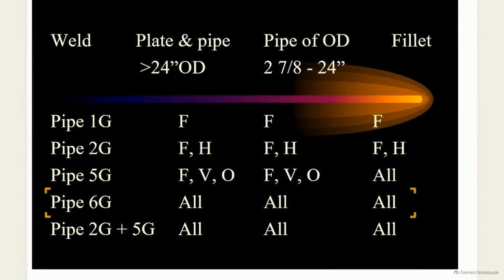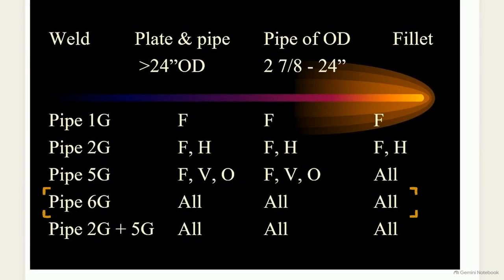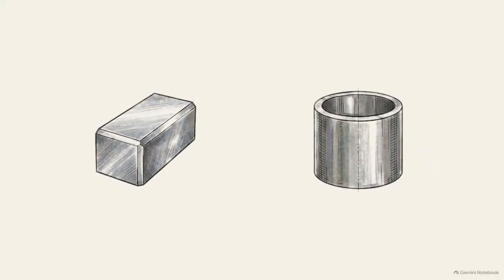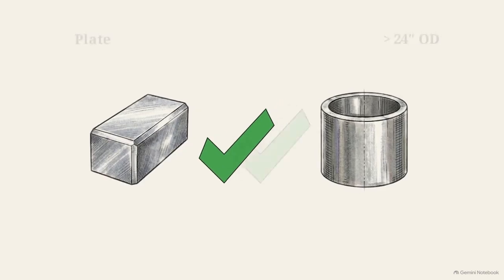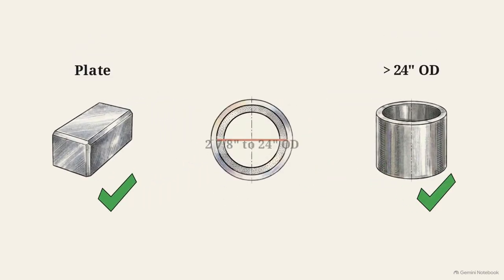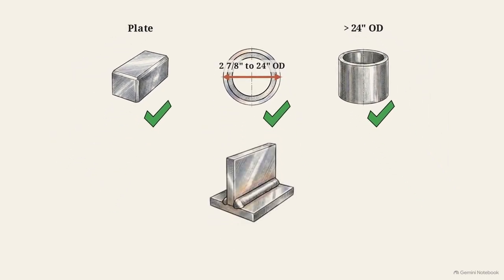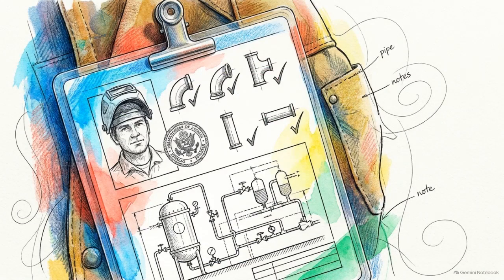We'll look at the fourth row labeled Pipe 6G. Note the designations in the subsequent columns. Successful completion of this test qualifies the welder for all positions on plate and on pipe with an outer diameter exceeding 24 inches. It also covers all positions for pipe diameters ranging from 2 7/8 inches up to 24 inches. Finally, the qualification extends to all fillet weld positions. Essentially, the 6G test removes positional restrictions for this welder on the production floor.